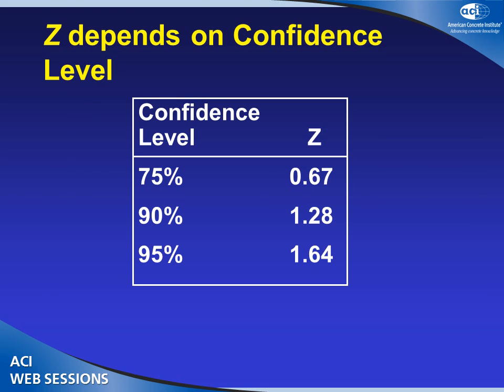The Z value, which is applied to the uncertainty of the strength correction factors, is just taken from the normal distribution for the various confidence levels. And so you can plug and get an answer that way. Again, what you'd be saying is I've got this in-place strength, and based on the tolerance factor method, I'm going to get some equivalent specified strength such that I'm quite sure that 3 times out of 4, or a 75% confidence interval, or 19 times out of 20 for a 95% confidence interval, the area that's less than the equivalent specified strength is less than the 10% fractile.